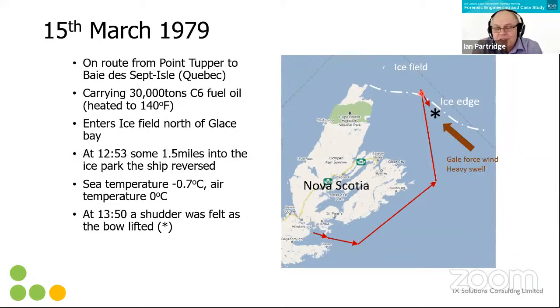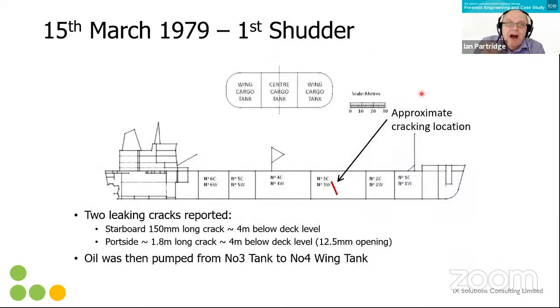At 12:53 in the ice field, they couldn't go any further. They got about 1.5 miles into the ice field and had to back out. Roughly an hour later, as they were backing out, a shudder was felt and the bow lifted. At the time, they had gale force winds and some heavy swell. This was the first shudder. Everybody was running around the ship. Somebody looked over the side.